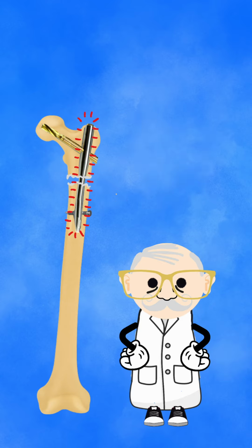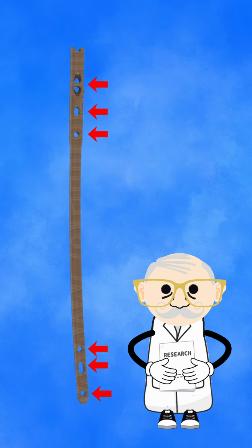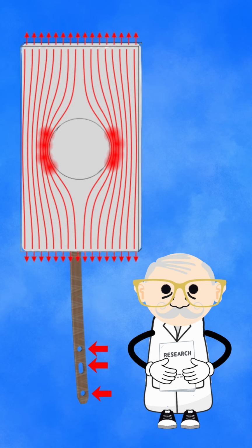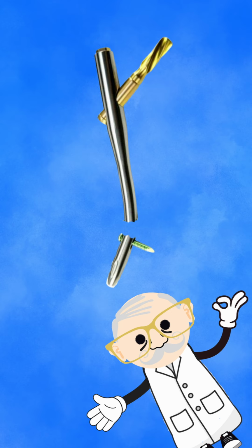If the fracture doesn't unite because biology is weak or the construct leaves a persistent instability, the nail becomes the main bridge across the fracture, and with cyclic loading, it can initiate microcracks, often at stress concentrators like locking holes, because stresses spike at the hole rim as internal force flow detours around the opening. Over time, the microcrack propagates until the nail fails by fatigue.